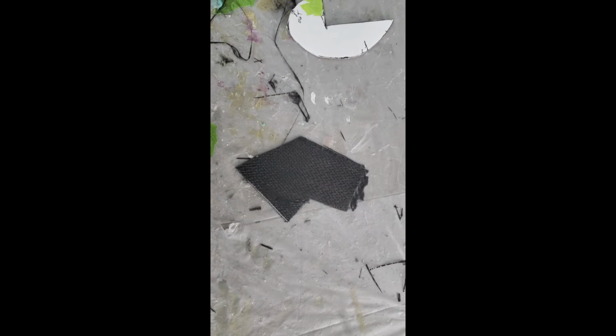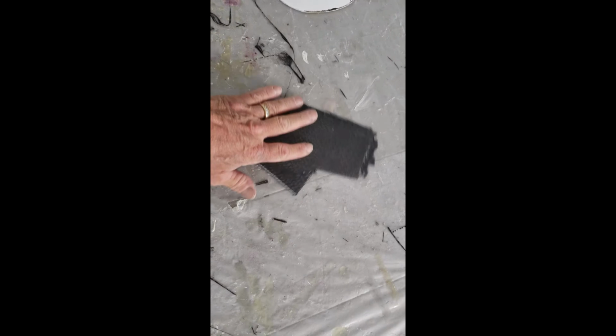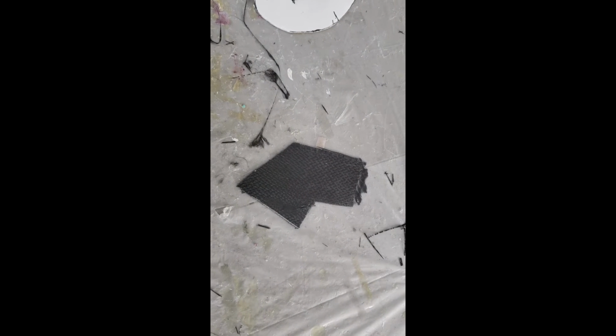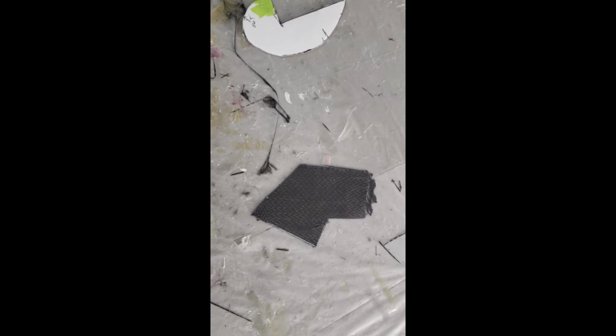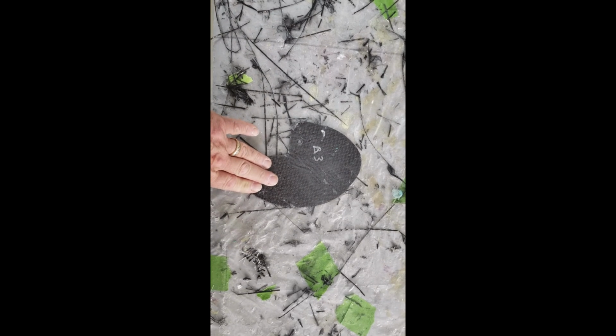The ribs are first made by creating patterns for how these ribs will fit tightly inside the armrests. Then I made a big slab of carbon fiber, just flat, plain. And I did it right here on the table, just used it as my backing. And just did 4 layers of the carbon fiber. That's 24 total thickness on the carbon fiber. And then use the pattern to cut out the individual ribs. Then once the ribs are made, they are put inside this area to provide much more support. You can see there's one more to go in here, 3 on each side.